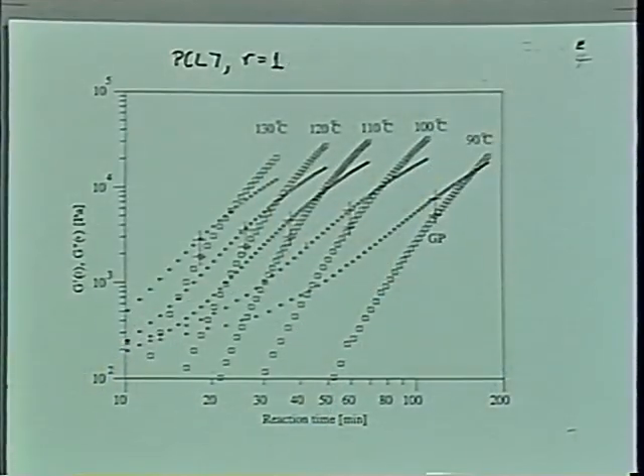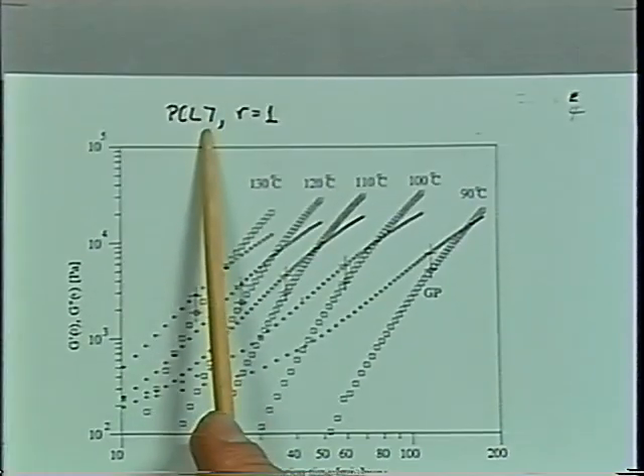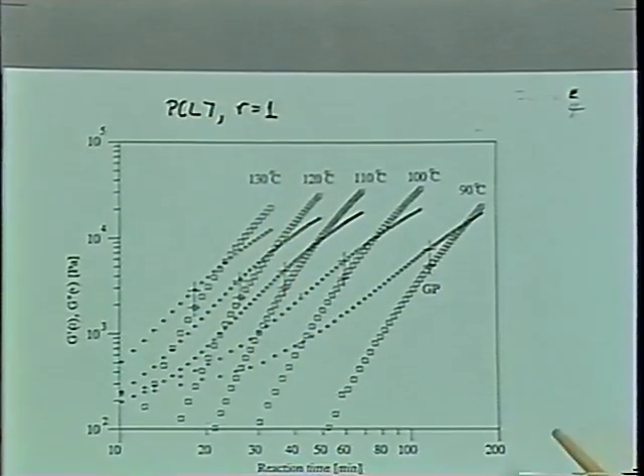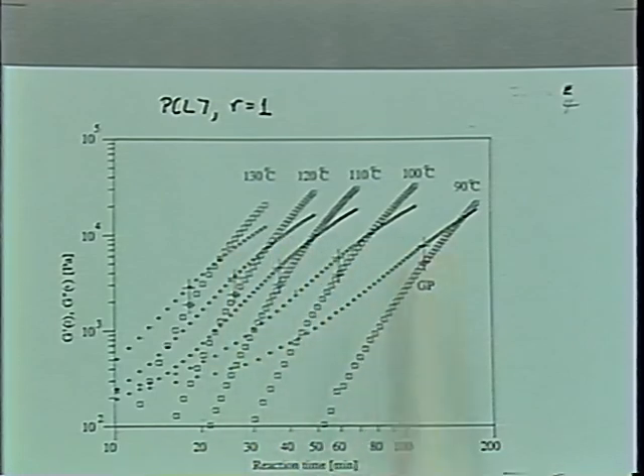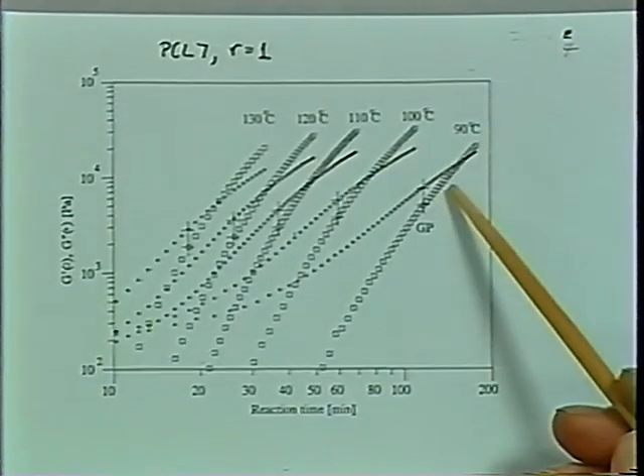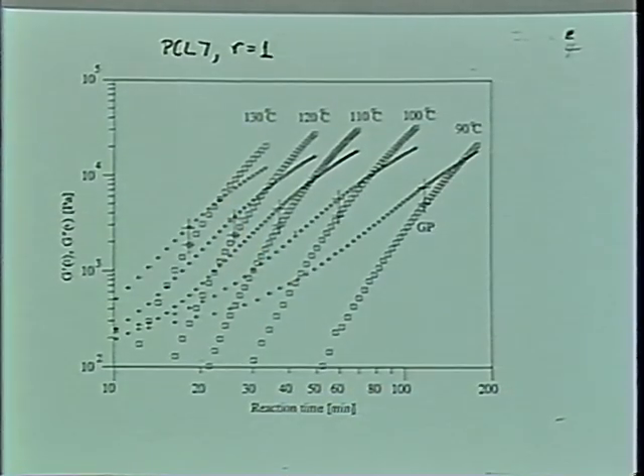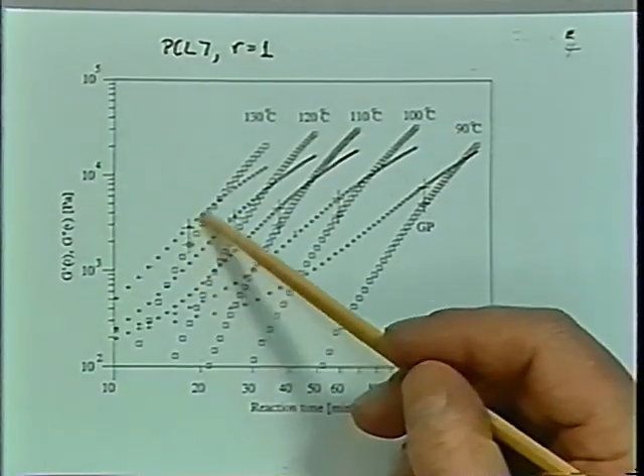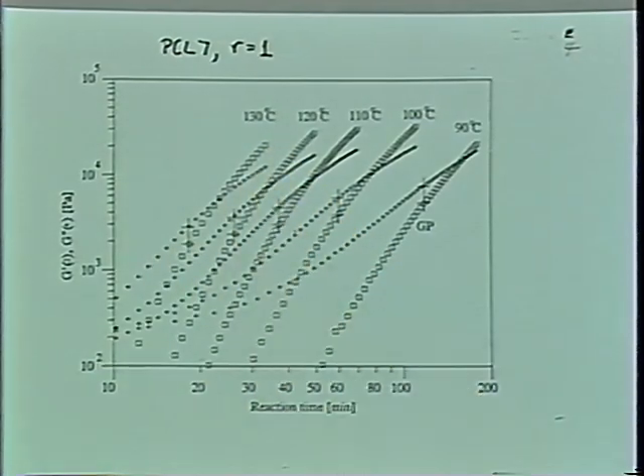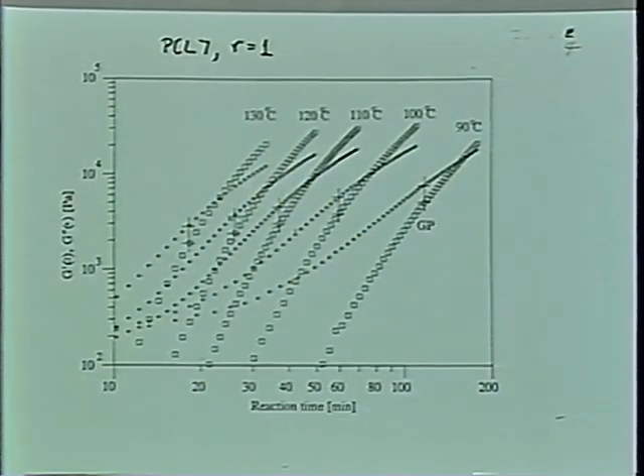Then Aki reacted materials at different temperature. He took the 7,000 molecular weight at balanced stoichiometry and reacted it at 5 different temperatures. With increasing temperature, the reaction speed increased. You have G prime coming up very quickly and G double prime over like this. It's a continuous evolution of properties. Now, where's the gel point? How could we measure the gel point? And Aki had a very nice idea in doing that. Let me describe that to you.